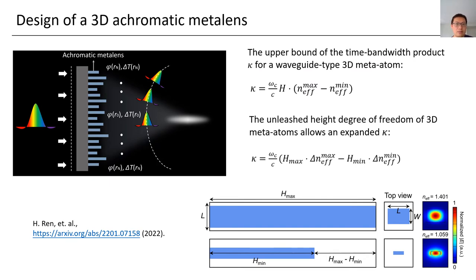So, how do we design an achromatic metalens? In general, we need two profiles. The first profile is, of course, the lens profile, where we can achieve the focusing of the light. Once we take the first order derivative of this lens profile, we find the group delay response, which means that once we do the focusing, we simultaneously introduce chromatic aberration if you have broadband illumination. So the second profile that we have to adjust is the group delay profile, where we can compensate this chromatic aberration, which is a temporal response, so that the broadband illumination can be focused down to a single focal volume, the single focal plane.